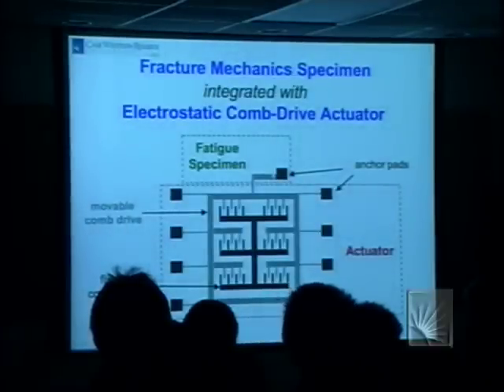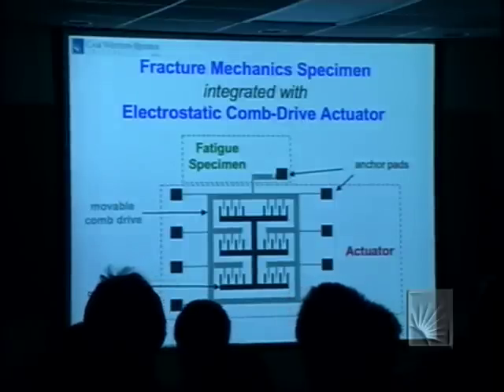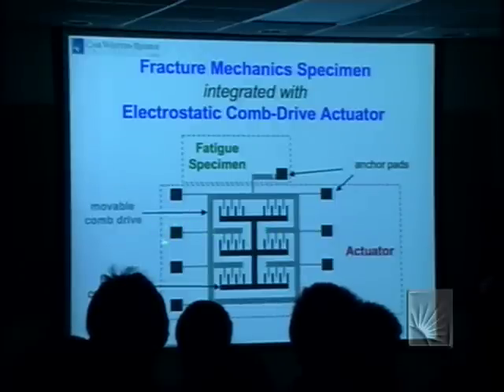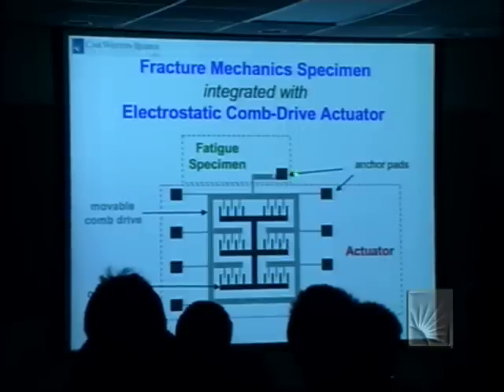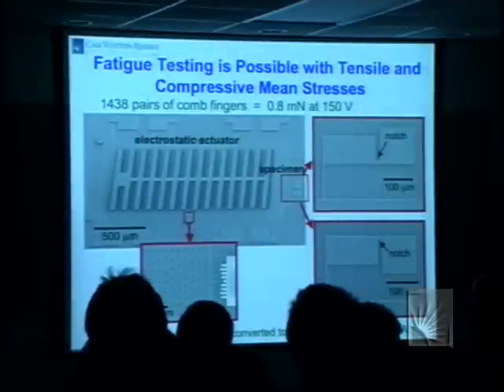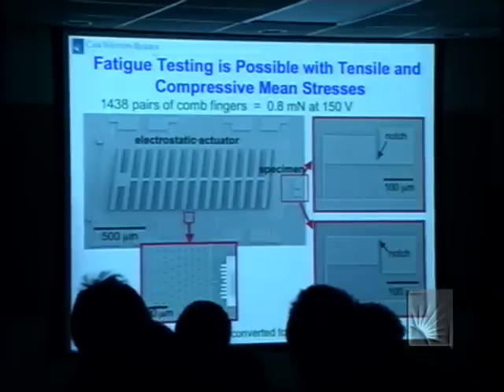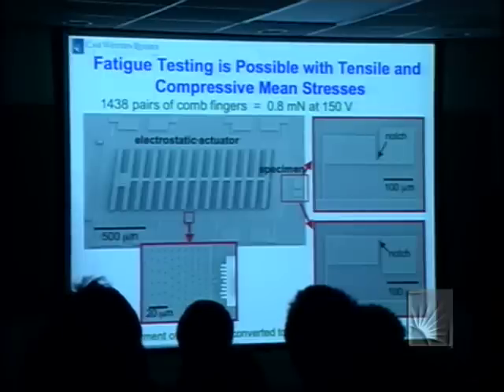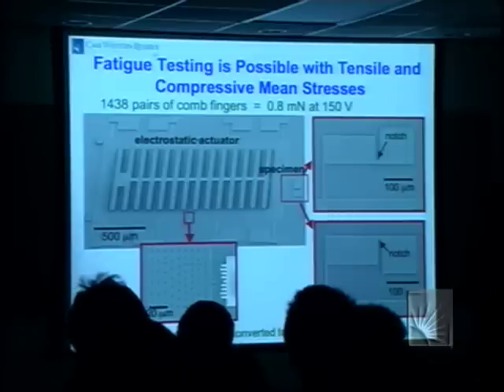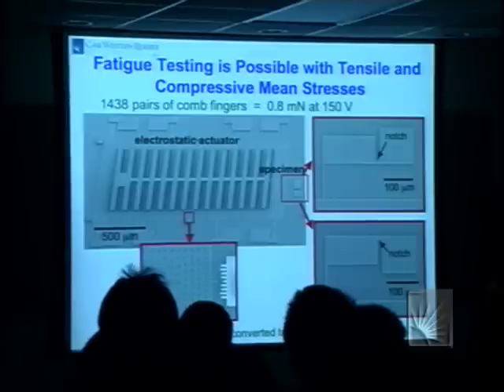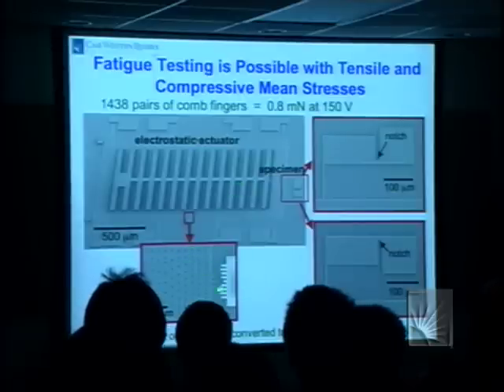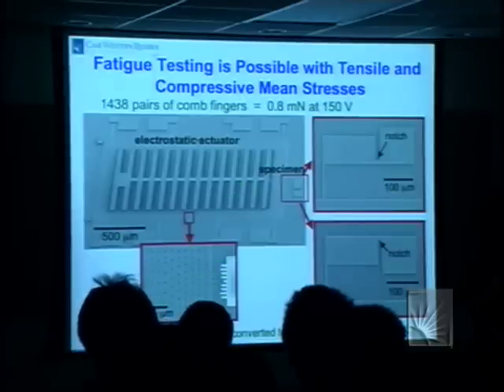And this is the type of device. We use the same sort of interdigitating comb fingers that are used in the accelerometer in your car. When you apply voltage between these black and gray regions, this device will move downwards as shown here, and then this is our fracture mechanics sample. This is a close-up. Actually, it was a significant development challenge to make these devices, which had these 1,438 pairs of comb fingers. If you're not calibrated, 0.8 of a millinewton may not seem like a large force, but it's a very large force at the microscale or nanoscale. And we measure the movement using this vernier and calculate the actual stresses by finite element analysis.